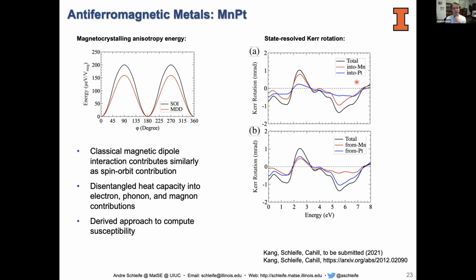One last interesting thing, because we talked about optics a lot, is shown on the right-hand side, where we calculate the Kerr rotation of the magneto-optical Kerr effect of this material. But because we have access to the individual states that contribute, we can tell for each peak in this case, spectral dependence here on the energy dependence, we can tell where each peak comes from. So all these transitions into manganese states or into platinum states, what dominates more in what energy range, and so on. So I think this provides us a very detailed insight into the magnetic structure and magneto-optical properties of